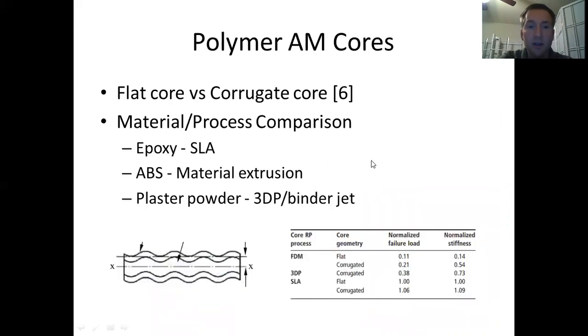And then there was another test done where instead of comparing different core densities, they tested a flat core as well as a corrugated core. That's what this bacon-looking image is down here. The corrugated core is a wavy feature, and they also experimented with different materials and different additive manufacturing processes. So they had epoxy with SLA, ABS for material extrusion, and the plaster powder for binder jet. And they showed from all their testing that the corrugated geometry always came out stronger, and the SLA epoxy was a stronger core than all the others. And they tested this using a bending test.